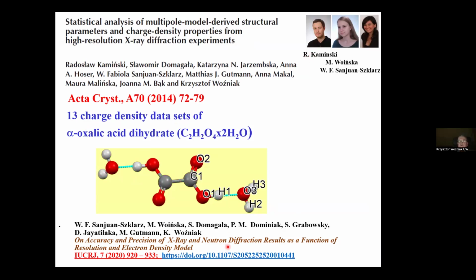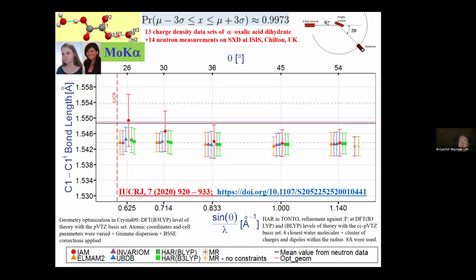And then we reused this data by cutting off fragments of resolution and reprocessing them from scratch in order to get dependence on resolution and on the model of atomic electron density used. So you can see results in those two papers. So for example, let us take just the central C1-C1 bond. And this is the dependence on resolution. And the maximal resolution is here.